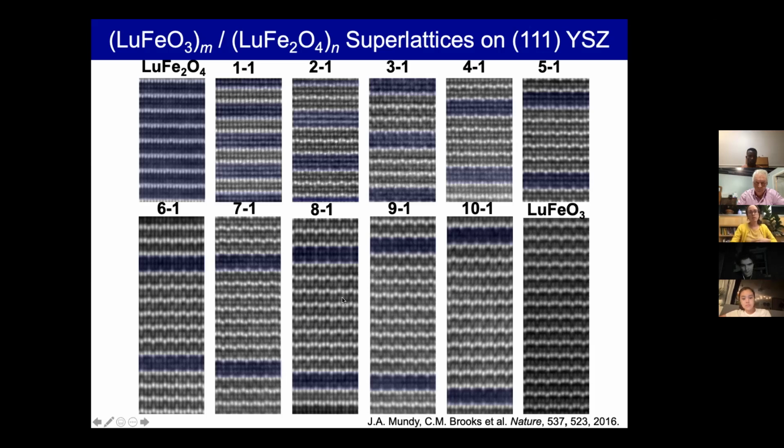Here, what we were able to do with the rumpling was make a series of compounds where we were changing the layering. In this end member compound, the atom displacements are about 40 picometers, and at the opposite end of the distortions, it's 0.